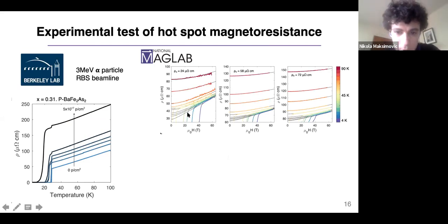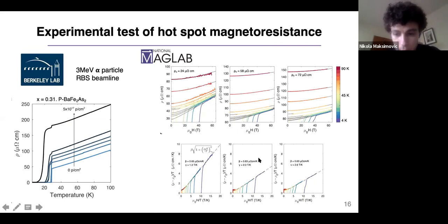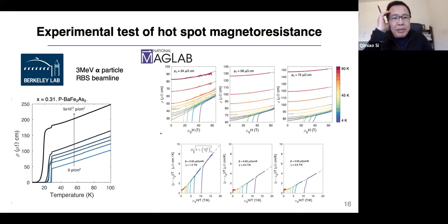So shown in the black lines are the calculation curves, the modeling based on Alex Koshelev's model. And in all cases, we can do this simple scaling relation where we divide resistivity by temperature and magnetic field by temperature. And as you disorder the system, the magnetoresistance decreases overall, and the coefficients of the scaling function change slightly. Nikola, do you mind if I interrupt just for 1 second? Sure, yeah.